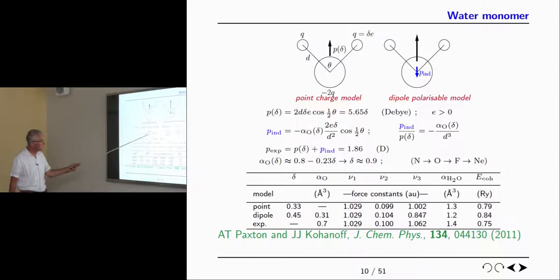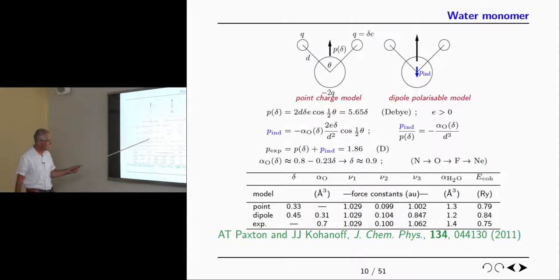Now if I compare these two formulas, I can replace the electric field by terms in this P of delta. So I get that the ratio of the induced dipole to the point charge dipole is given by that. And if we knew the polarizability of the oxygen atom as a function of its charge, then we'd have a closed set of equations that we could solve, and we'd then have a model. We know that the experimental dipole moment must be the sum of the two, and unfortunately this didn't work.